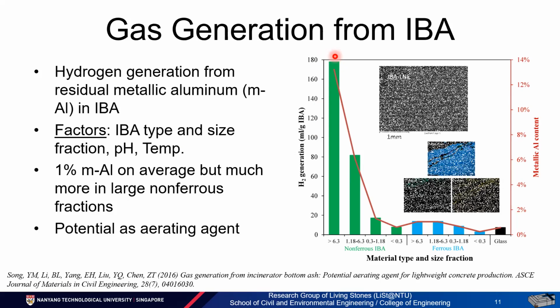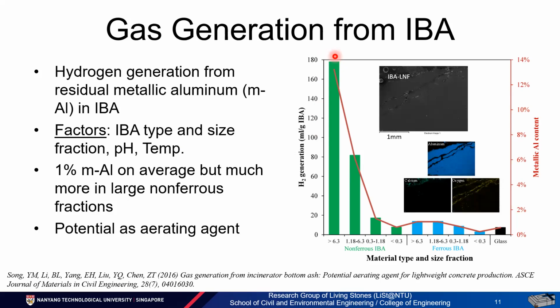When we observe those particles on the SEM and BSE image, you'll often find a large chunk of metallic aluminum in the non-ferrous IBA in the larger particles. We believe that's because of the high ductility of the non-ferrous metallic aluminum, which will basically be present in the non-ferrous part, especially in the larger particles.